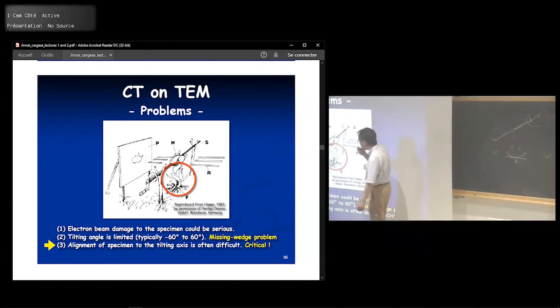especially in TEM, there are a couple of problems. One is, again, the beam damage. This means that you keep on shining the electrons, then you eventually burn the sample. And another problem is what we call the missing wedge problem. In this cartoon, we can freely rotate up to 90 degrees or 360 degrees. But inside the TEM, there's a problem so that we cannot tilt the sample, rotate the sample up to a certain angle. That's another problem.